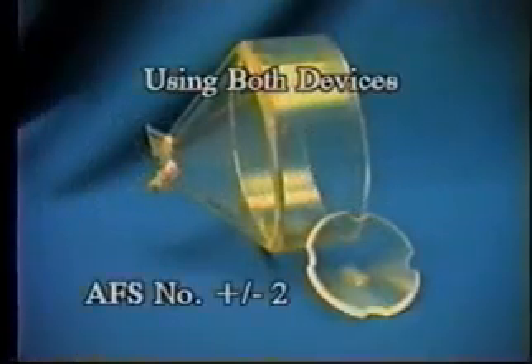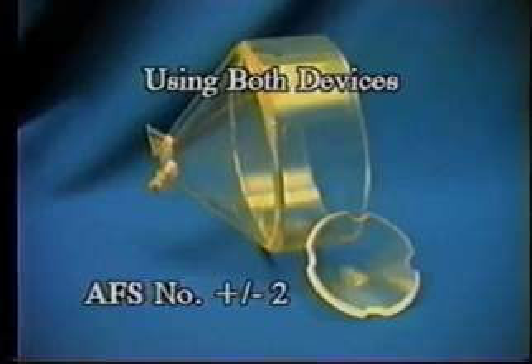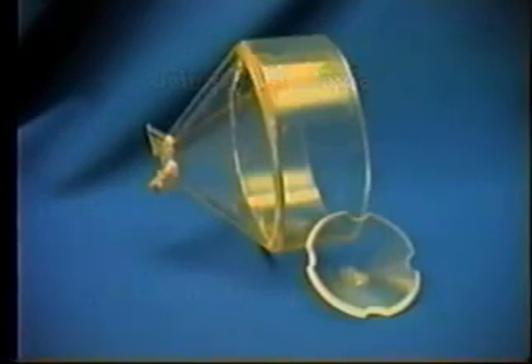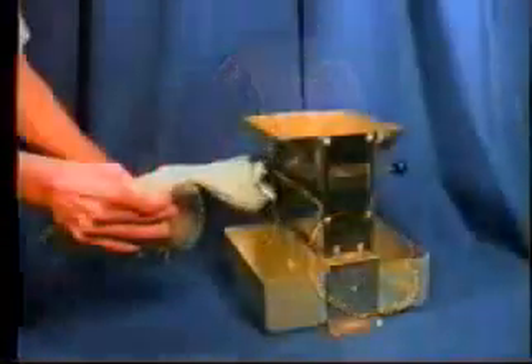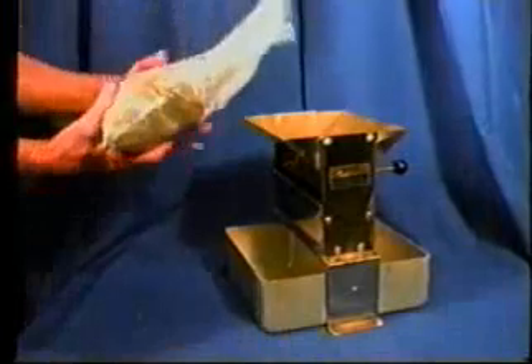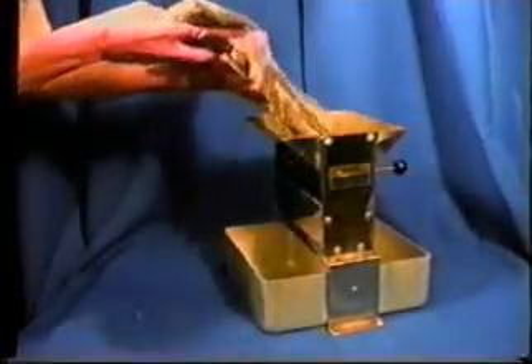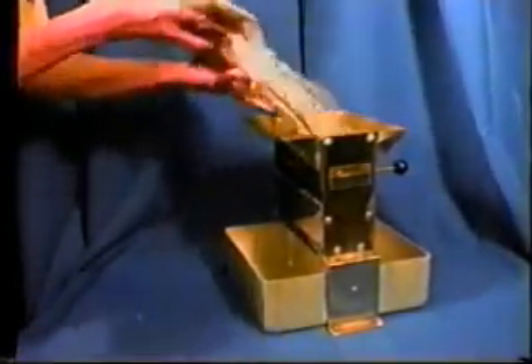Using both of these devices in a sand bin further enhances the reblending. Tests have shown the sand will be maintained in a range of plus or minus 2 points variance in AFS number. Let us emphasize again, gathering of sand samples for testing must be accomplished meticulously.